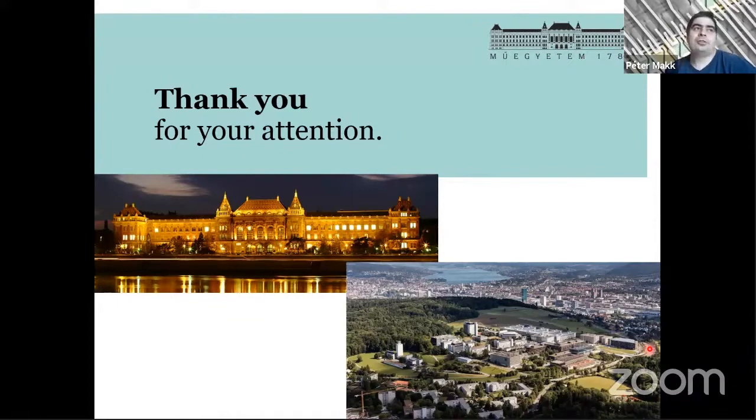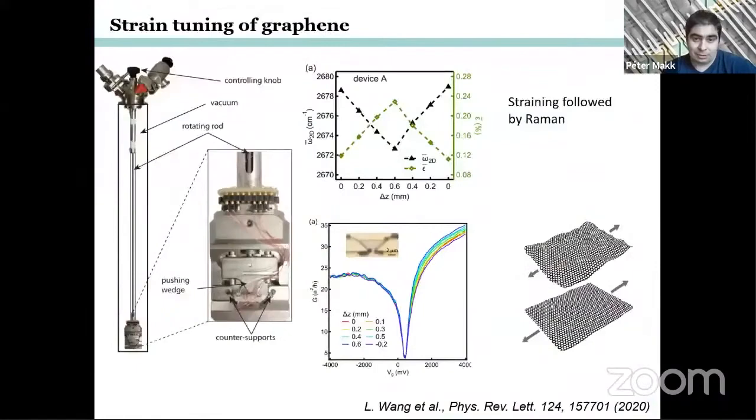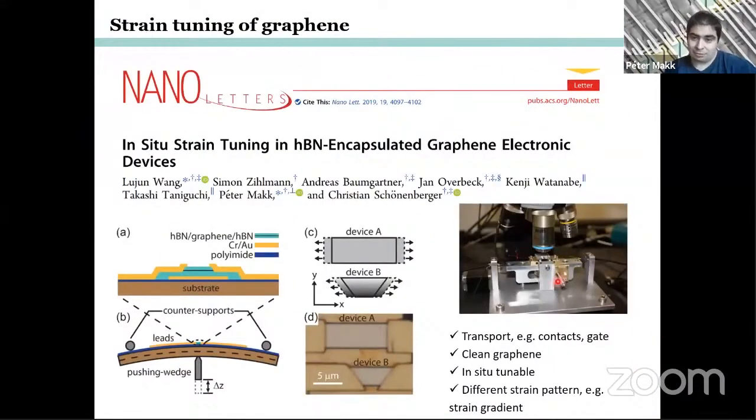That's a conventional Raman setup which we have used. Okay, so there are two things. One is that we measured Raman at room temperature. I go back to the figure, at room temperature. It's a conventional, I think you can say safely, 500 nanometer spot size. So this is your resolution. In this paper, we have maps around the sample, like let's say these 10 micron flakes. You can check how homogeneous a uniaxial strain you can generate, or in this case, we generate a bit of biaxial strain.